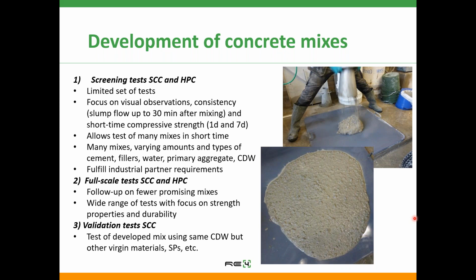As Ruben mentioned, they need, for example, some early strength development in order to demold and work with the elements as soon as possible after casting. And in this way, we can vary a lot of different properties, like the primary aggregates, replacement level of CDW, different cement content, and so on, in a relatively short time to really optimize, to get as high as possible CDW replacement and still fulfill the industrial partner requirements. Because, of course, as Ruben mentioned, CREAG Concrete have properties they want to be fulfilled. After screening tests, identifying some candidates, you could go for a more full-scale test program on larger batches and also a lot of other properties and also durability properties.